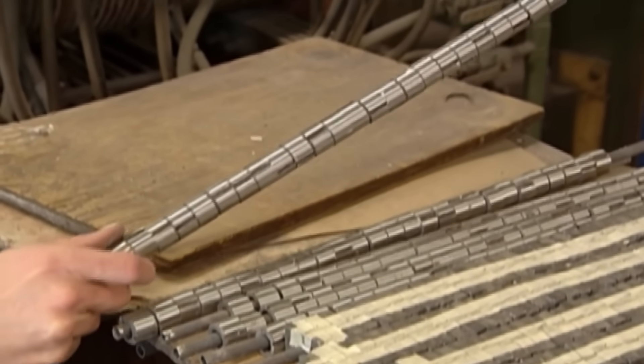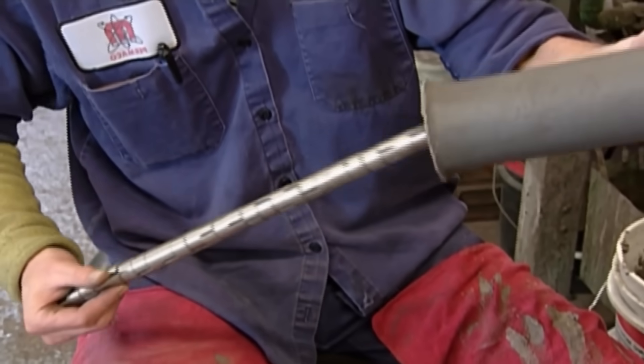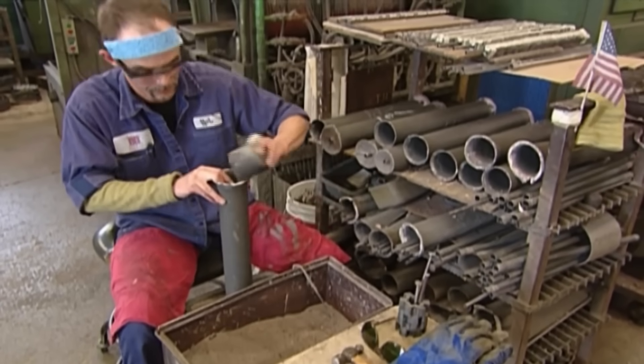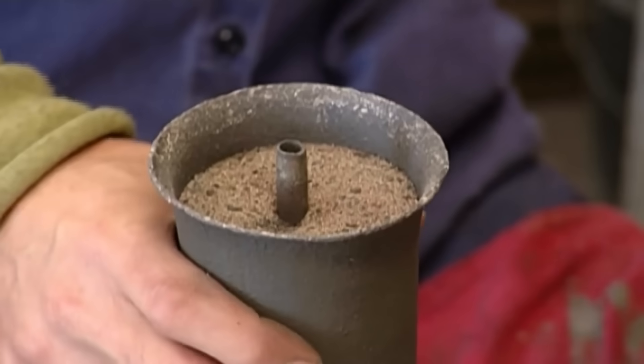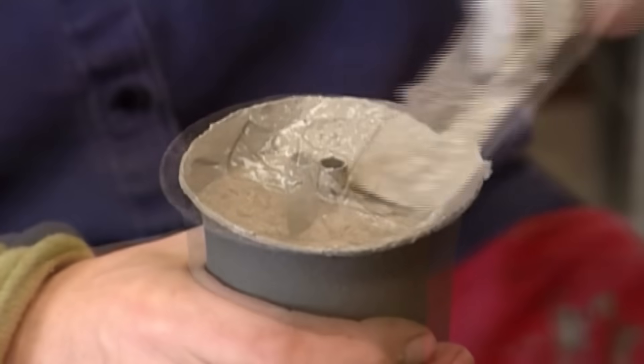These ring-shaped magnets, for example, are threaded onto a copper pipe. This ring-covered pipe is then placed in a much larger tube, centered by packing silica sand tightly around it. The sand will hold the rings in position during the next step. After the tube has been sufficiently packed, its ends are sealed with concrete, allowing the inner copper tube to protrude slightly. Then it goes into a different electrical furnace, which heats the tube full of magnet shapes until it's red hot.